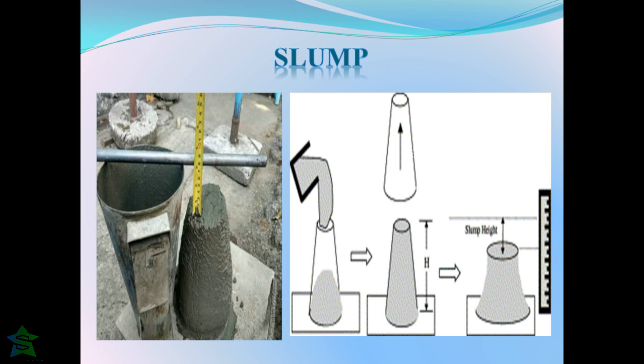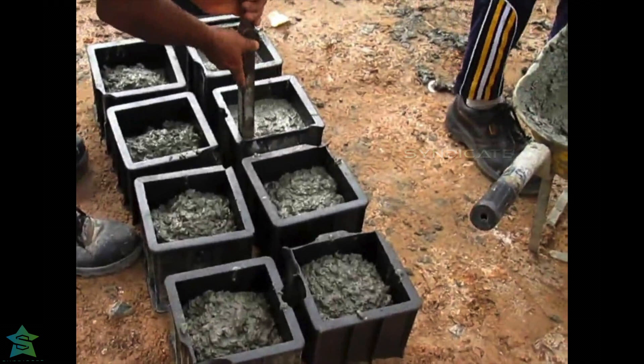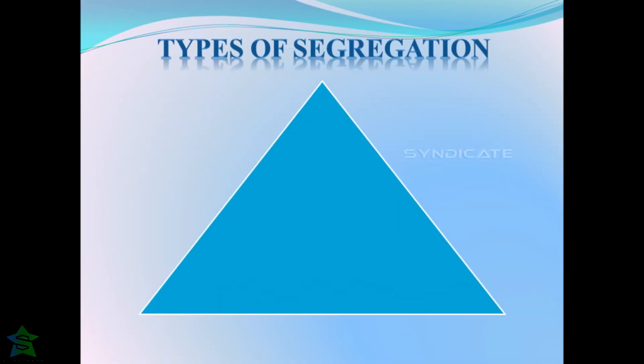In recent times we use concrete with very high slump, particularly in ready-mix concrete. The slump value required at the batching point is 150 mm and at the pumping point would be around 100 mm. Cubes are cast at both these points, hence care must be taken during compaction of cubes with high slump concrete, failing of which leads to segregation and decrease in strength.